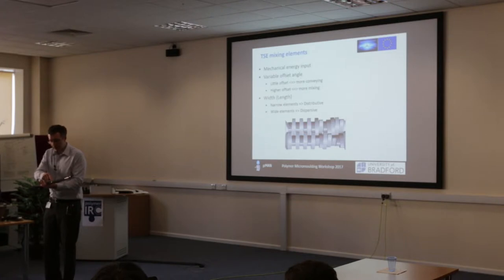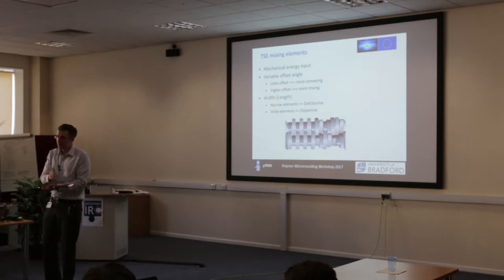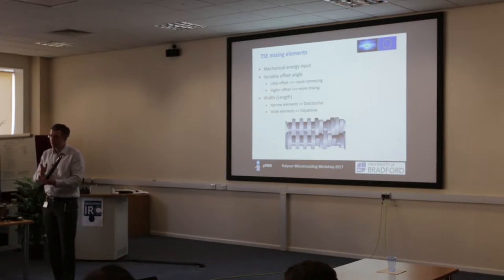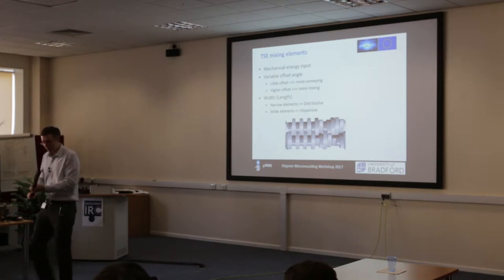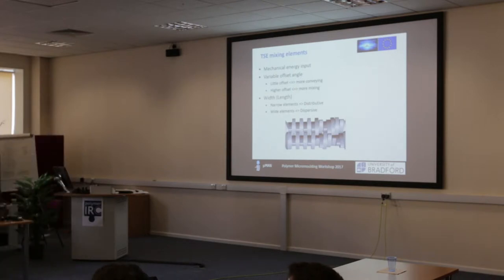If the kneading elements have quite a shallow angle, if they're 30 degrees apart, then it doesn't provide a great deal of mixing. If they're at 90 degrees to each other, then it provides the maximum levels of mixing. And if you get the screws right, you should be able to put them on the desk next to each other and roll them along, and they should intermesh perfectly. So you can see the actual mechanism of the screws. So if you want to pass those along and try and keep them together.